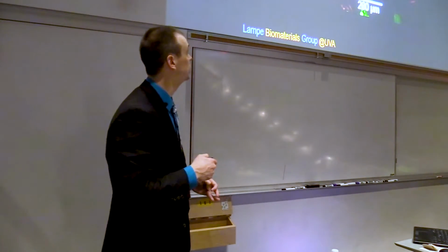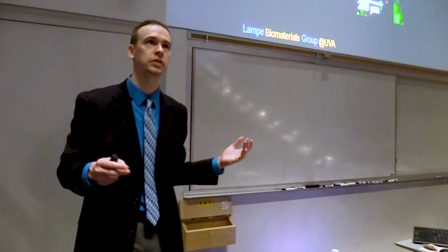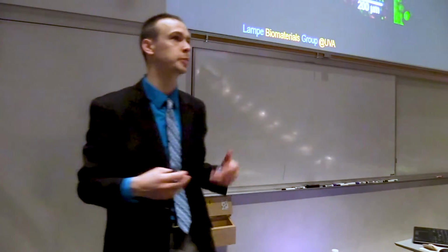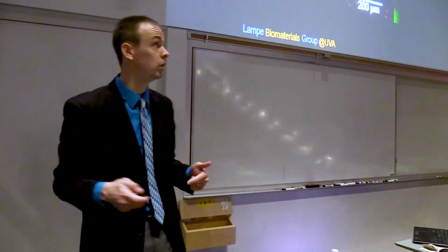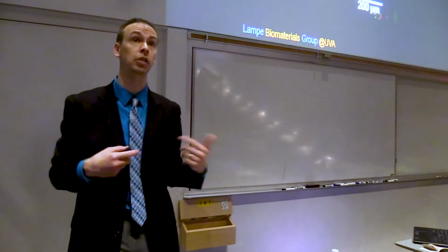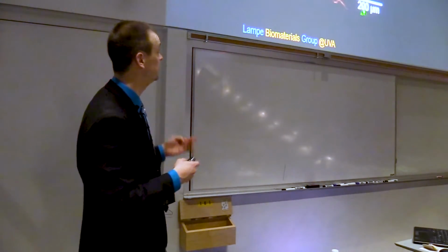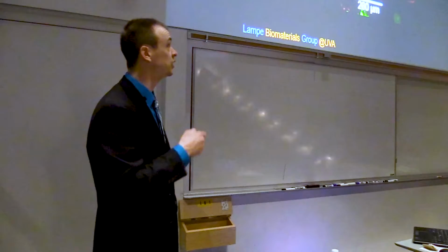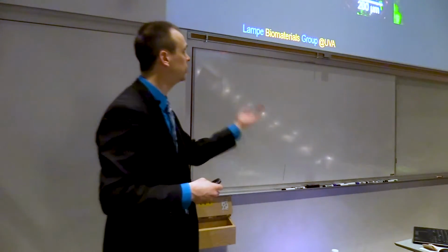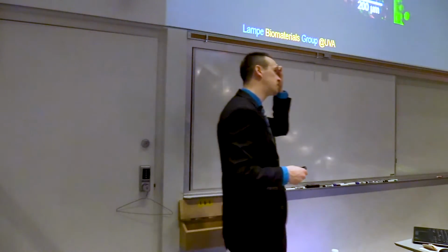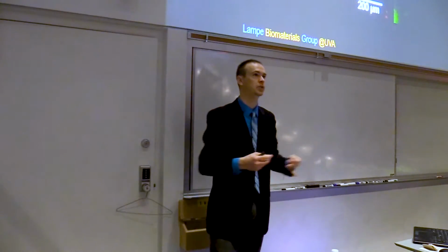So these are fibers, just polystyrene fibers, so it's a pretty easy process to make electrospun polystyrene fibers. It's a little bit harder to embed them in a 3D hydrogel along with the cells, but we did it, obviously. But you see the cells like the fibers, and those fibers were specifically designed to be on the size diameter scale of a mature axon, right?